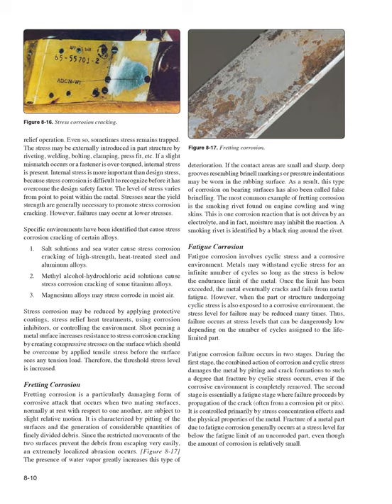life-limited part. Fatigue corrosion failure occurs in two stages. During the first stage, the combined action of corrosion and cyclic stress damages the metal by pitting and crack formations to such a degree that fracture by cyclic stress occurs, even if the corrosive environment is completely removed. The second stage is essentially a fatigue stage where failure proceeds by propagation of the crack, often from a corrosion pit or pits. It is controlled primarily by stress concentration effects and the physical properties of the metal. Fracture of a metal part due to fatigue corrosion generally occurs at a stress level far below the fatigue limit of an uncorroded part, even though the amount of corrosion is relatively small.